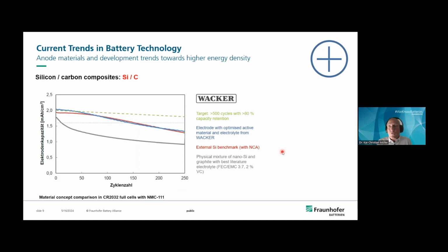It's not so easy to incorporate silicon into the batteries. You can imagine the volume expansions are very difficult to handle. And one example you can see here, where you have here the cycle number and here the electrode capacity. If you just mix the silicon and the graphite, the decrease in capacity is quite strong, especially in the beginning of the cycle life. A value would be a remaining capacity of 80%. This will be reached at already 20 cycles, which is not good enough for an application.